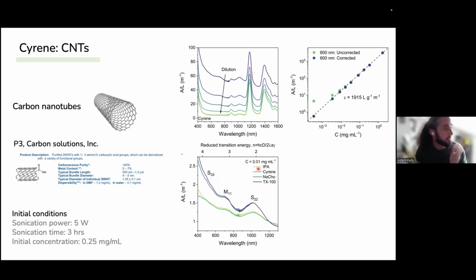Now, we also produce dispersions in IPA and sodium cholate. And what we found was that the width of this S22 peak is a measure of how many bundles there are in your dispersion. Both of these have fairly broad peaks, indicating that we still have quite a lot of bundles.